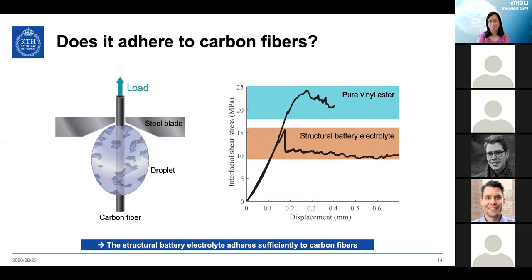To characterize the adhesive properties between carbon fibers and the structural battery electrolyte, a drop of monomer and electrolyte is placed on a single carbon fiber and solidified into a droplet. The droplet is held by steel blades and the fibers pulled out. This is measuring the adhesive interfacial shear strength. The results show that the structural battery electrolyte is not far from pure vinyl ester in adhesive properties, even though the adhesive surface area is greatly reduced by the phase separation of the structural battery electrolyte.